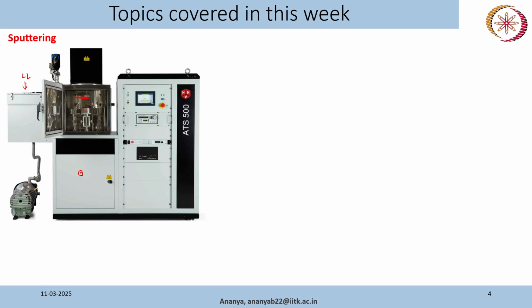Another advantage is that sputtering is not very directional. So if you have a step on your wafer, say you have already done some lithography and you have this kind of a step, and you deposit a film using evaporation, then because in evaporation the materials move in a straight line, the film coverage at these portions will be less. So you will get a good film here, but not here. In the case of sputtering, because it's not directional, you will get a uniform film on top of your structured film. So that is another advantage. If you need that, then that is helpful.